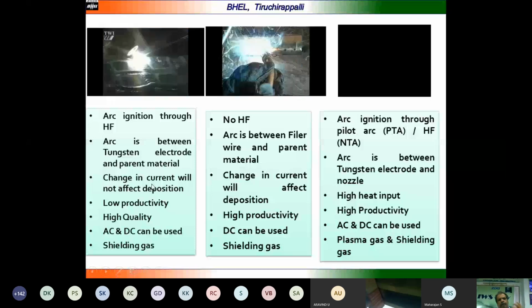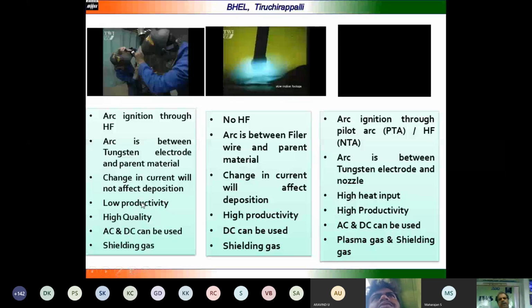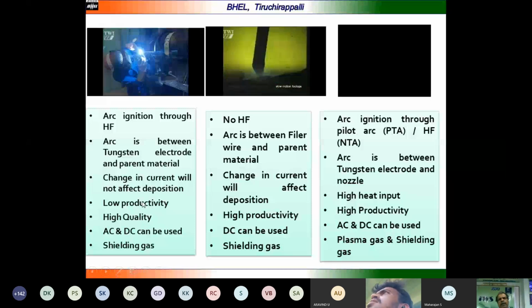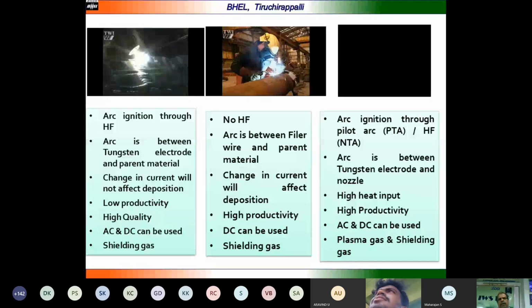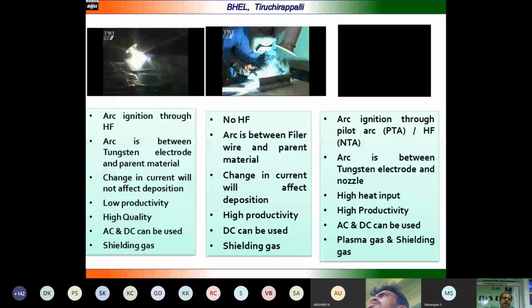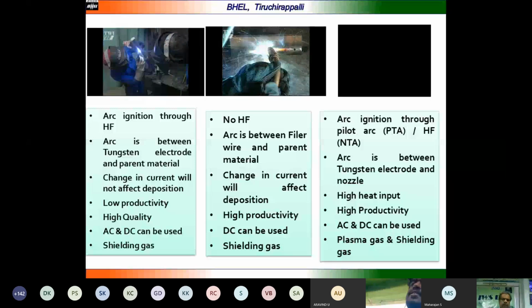For example, I can take a task to weld a 7.4 mm thick aluminium alloy AA2219 with a square butt joint preparation without root gap, and the weld should be completed in a single pass. Then the shielding gas we use is helium, and we establish the parameters. So for deeper penetration and a good quality weld, we can go for helium, but the cost is high. The gas consumption is also high there. But in argon, there is commercially pure argon.